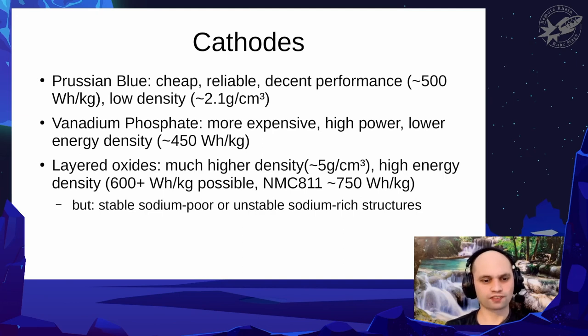The problem with that is you need more volume, and all the gaps in the volume need to be filled with electrolyte. And so you need more electrolyte, and that means it weighs more. And so the ultimate energy density will be worse than if you had a material that has a higher energy density. Also, the cells take a little bit more volume.